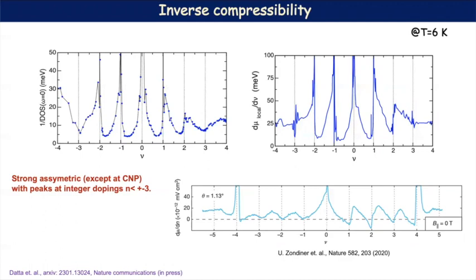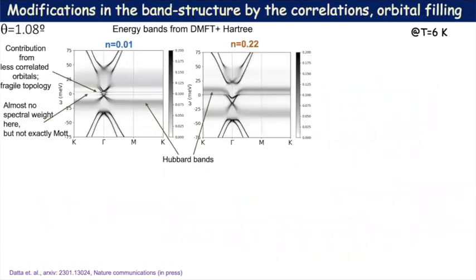So now, just to understand these cascades a bit better, let me show you the spectral functions. So here I have the spectral functions, and this is at 0 doping. The spectral function looks like this, and you can see that there is a significant drop in the weight near 0, and there are these Hubbard bands. But we still don't have a Mott insulator here because of the contribution from the less correlated orbitals at the gamma point, which comes due to the fragile topology, as I mentioned earlier. And then as we dope the system, the chemical potential shifts. And so we have these asymmetric Hubbard bands here, but the filling mainly happens in these less correlated orbitals, which you can see because of this filling here, we have this deformation in these itinerant electrons.